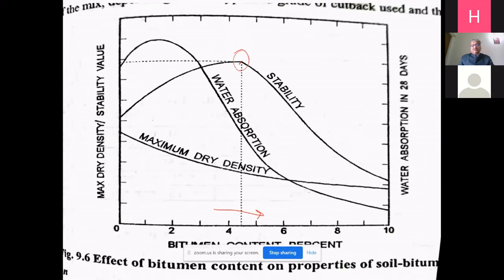Similarly, this maximum dry density also goes decreasing, because the specific gravity of the bitumen is 1 only, 1 or 1.02 or 0.97, while the desert sand has about 1.7 or 1.8 as the specific gravity of the desert soil. So that is why when you are adding the bitumen, the combined dry density starts coming down.